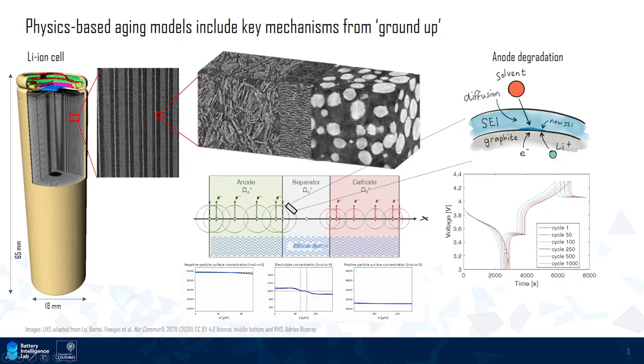Let's maybe zoom into a battery, on the electrode and the electrolyte you just mentioned. What happens actually inside these batteries, speaking chemically or thermophysically? There are a lot of different things going on here. They range from electrochemical effects, like undesirable oxidation and reduction of the electrolyte, through to growth of what's called the solid electrolyte interphase, which is a special layer that grows on the electrodes, which protects them, but also consumes lithium, which is what we want to have our capacity, right? We know, for example, that this layer, the SEI, on the graphite is a key part of degradation. And we know that this layer grows all the time as a function of voltage and temperature. So even when your battery is sitting there, not being cycled, this layer is still growing. And I'll talk about that a little bit later on.